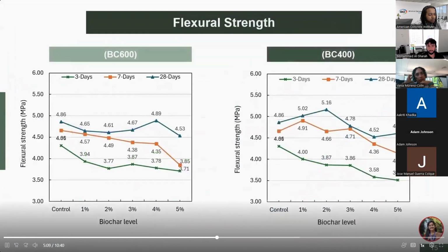From the flexural strength performance, BC 600 showed that the flexural strength slightly decreased up to 3%, but at 4% it showed higher strength than the control. On the other hand, BC 400 showed an increase in flexural strength up to 2% replacement, after which the strength gradually decreased. However, both types of biochar demonstrated satisfactory flexural strength performance, aligning well with the findings reported from the literature.